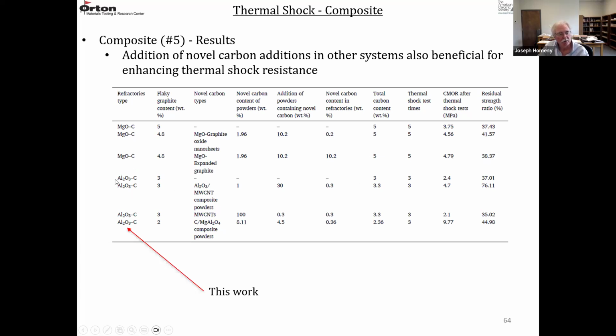And then here's some additional alumina carbon composites. These had 3 weight percent flaky graphite. And the second one here was reinforced with a multi-walled carbon nanotube. And there's a substantial increase in the residual strength from 37 to 76%. And then this one had, again, multi-wall nanocarbon tubes, and this one really did not show a great advantage.